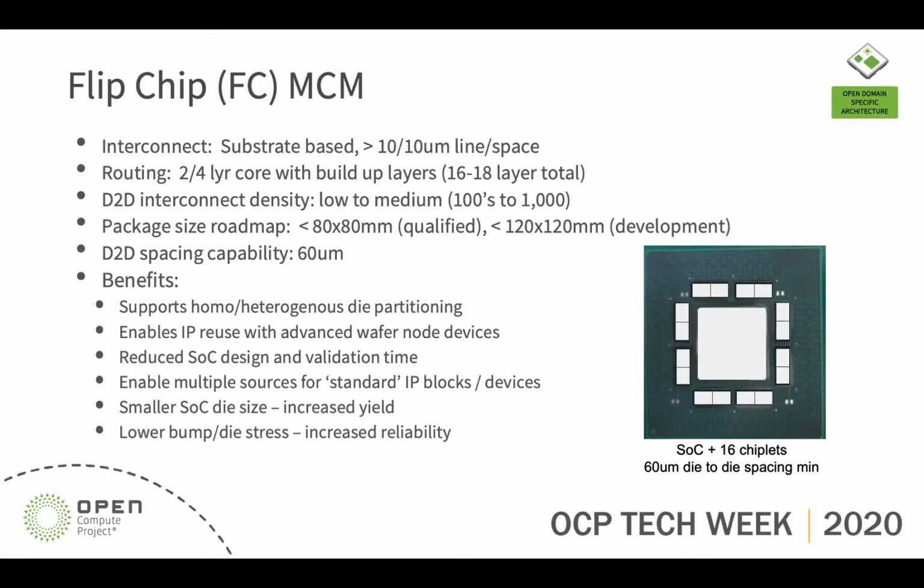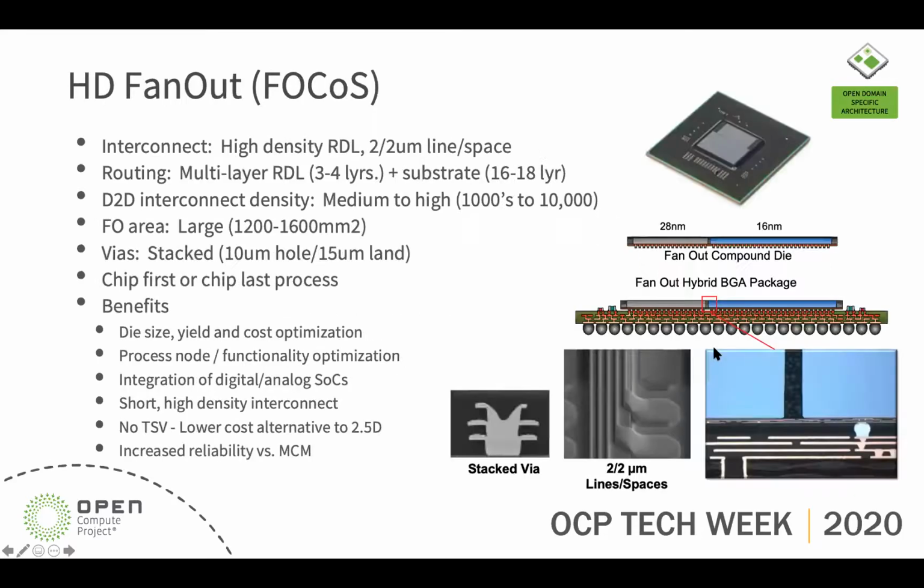You know, it really supports die partitioning and enables the use of IP dies such as SerDes, et cetera, for interfacing with your chips. High density fan out, for HD FanOut we call it FOCoS, but now we're using high density lithography based RDL. So we deposit an interconnect layer on a reconstituted wafer with different partition die or chiplets. And now we can go down to 2-micron line and space.